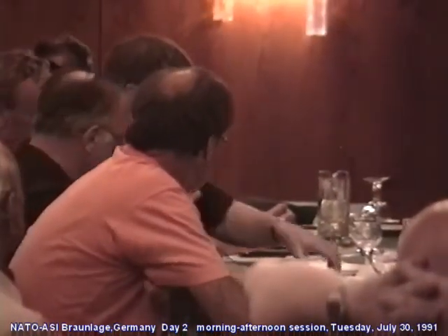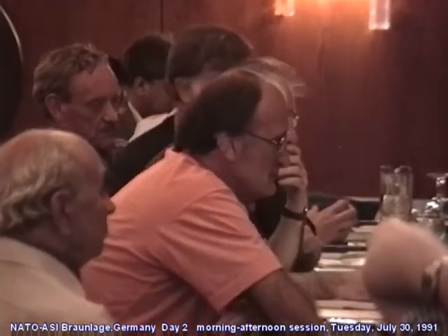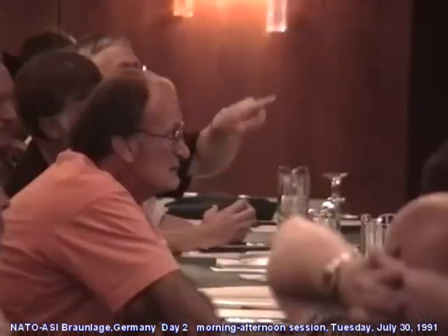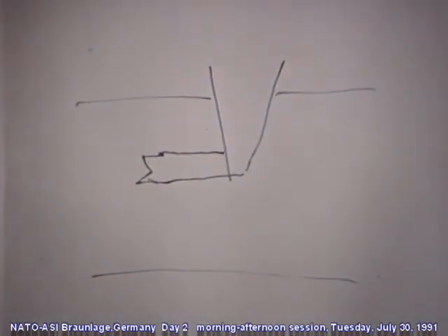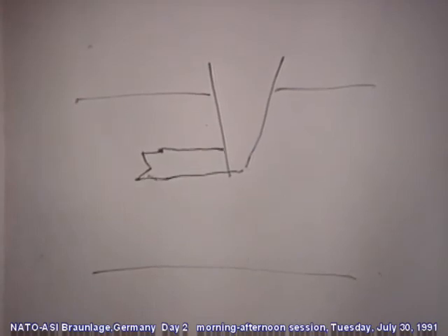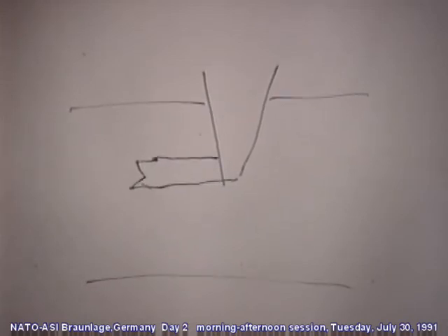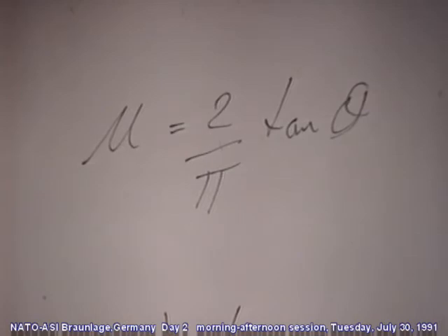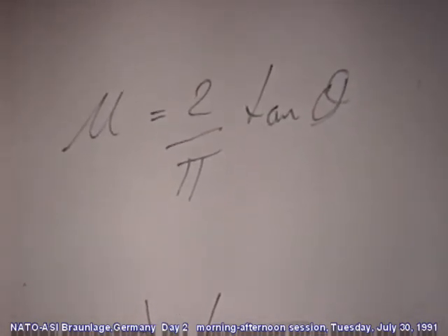I have a comment. If you could just put that transparency up. Professor Tabor made the point that the likelihood is that it will be subsurface plastic deformation which was the source of the friction deformation. Well, that's the classic relationship for the coefficient of friction for a conical indenter. It's geometrically similar, so it doesn't contain any material parameter. So it's difficult to see that if you have introduced a change in the rheology or ductility of the material by changing the temperature and the strain rate, it would manifest itself in the friction coefficient. I could see that it would change the hardness when you've been doing the scratch hardness experiment.